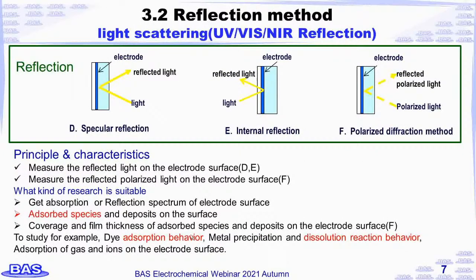Second, the reflection method is also performed in the ultraviolet, visible, and near-infrared regions. The typical reflection method is shown here. Light is incident on and reflected from the electrode surface, and is classified by different incident light and direction. By measuring the reflected light or the reflected polarized light on the electrode surface, we can get the absorption or reflection spectrum of the electrode surface to know the adsorbed species and deposits on the surface, and the coverage and film thickness of the adsorbed species and deposits on the electrode surface.